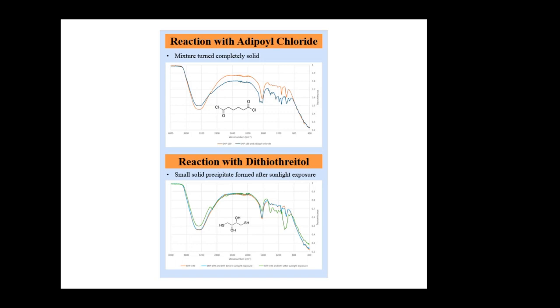Next, we tried the click reaction by mixing our polymer with Dithiothreitol and leaving it in the sun as our light source. We see an alkane peak emerging at about 3,000 wave numbers from the carbon chain in the thiol. Most notably, though, if we look all the way down to about 900 wave numbers, we see a new peak that is indicative of an alkene double bond, which is what we would expect to appear if our click reaction with the alkyne was successful.